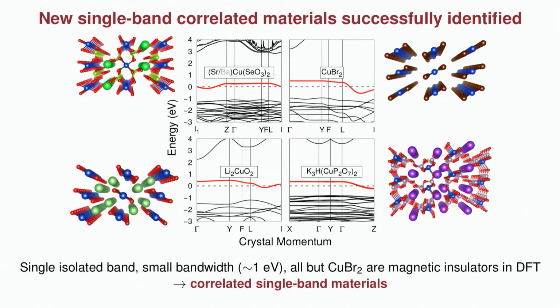We find that all of these compounds exhibit a magnetic instability, so that's another signature of the electronic correlations. And all of them except the bromide really are strong magnets, so they fully spin polarize even within the DFT, just the band theory level. So just like I showed you before for vanadium disulfide, already even within DFT, these compounds show strong signatures of electronic correlations.